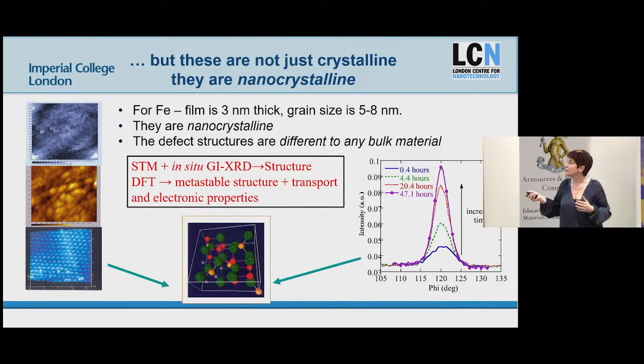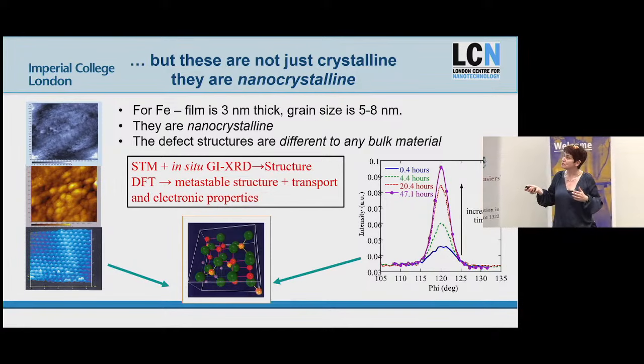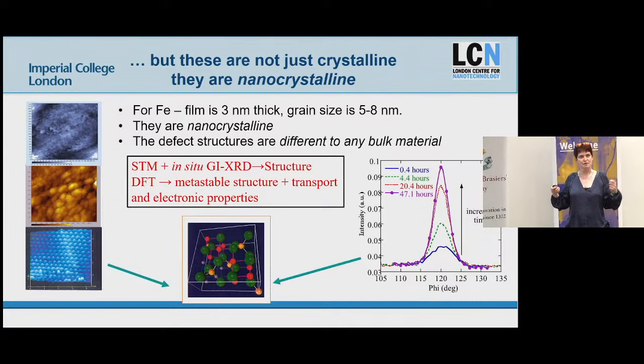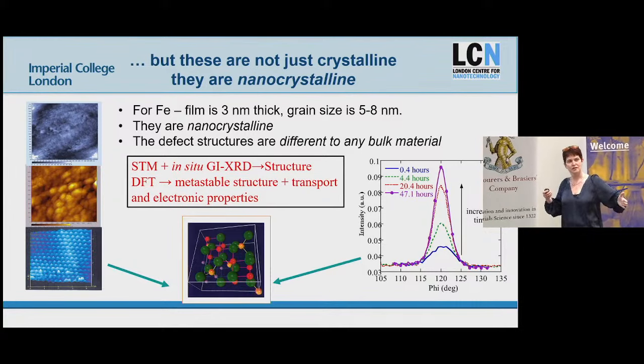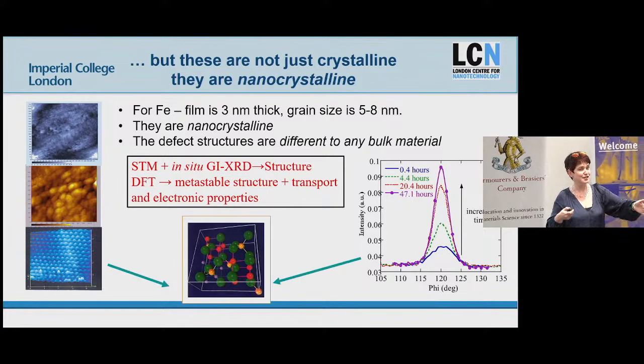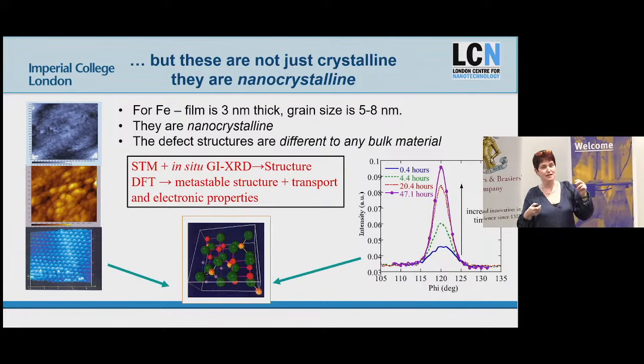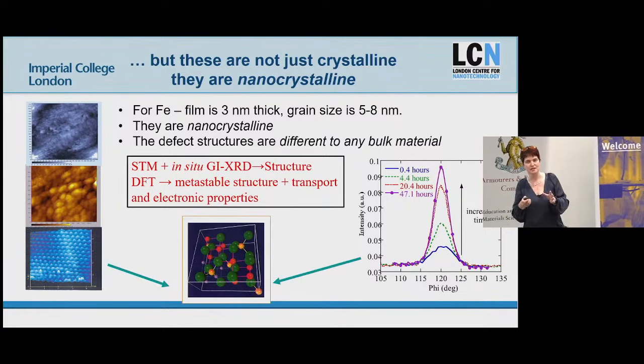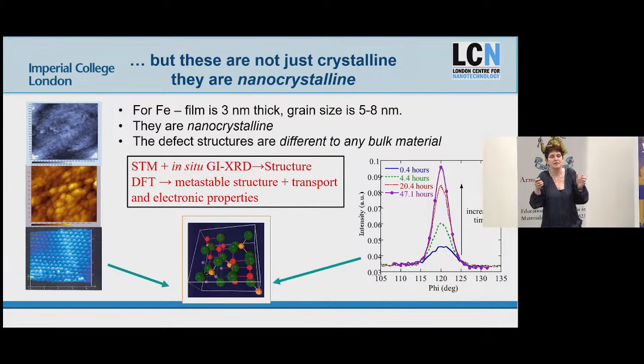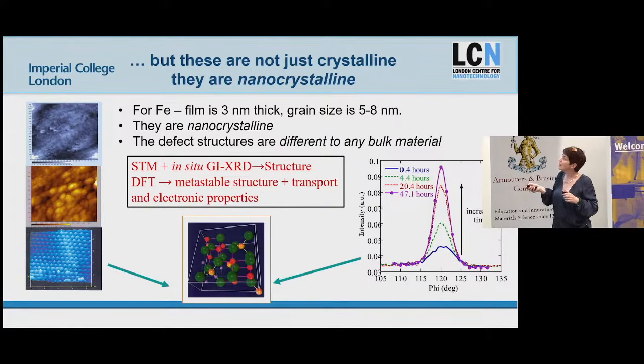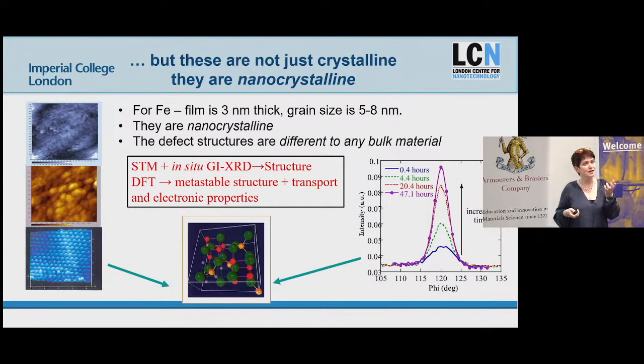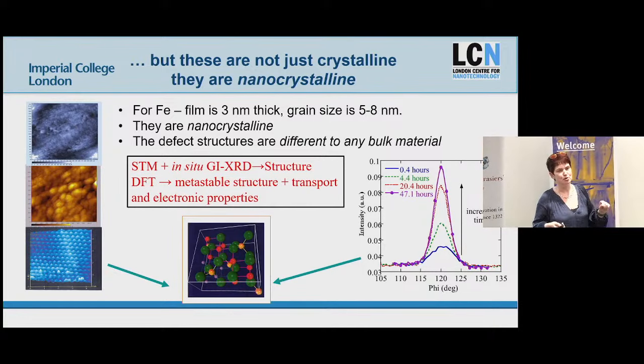And so we were able to understand how this structure forms by thinking about what the metal is doing in an environment. It's got a huge thermodynamic tendency to oxidize, so you get tons of nucleation sites on the surface, and they all grow a little bit and then stop because they're constrained. And then taking these data, we were able to show what the actual defect chemistry of those oxides are, and what you find is they're not the same as any bulk material.